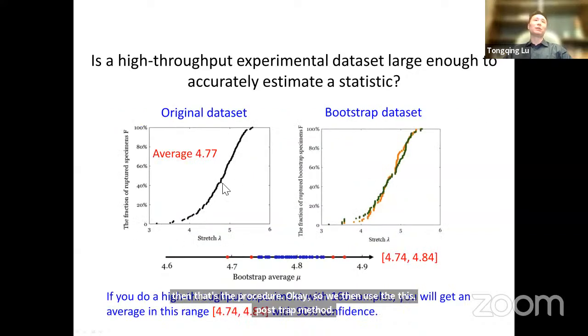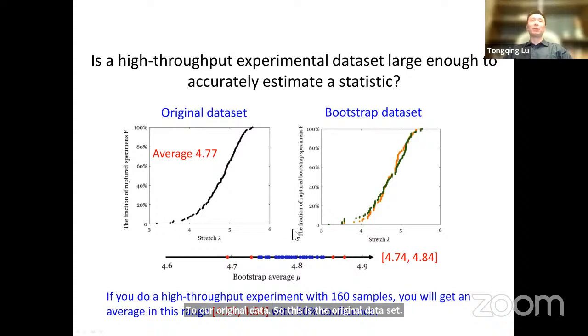So this is the original data set. We generate 40 bootstrap data sets. Here, just to show, are 2 representative bootstrap data sets. You can see they're similar to the original one, but they're not the same. The 40 bootstrap data sets generate 40 averages. They are plotted on this line. Remove these 2 and remove these 2, so the remaining is the 90% confidence interval.